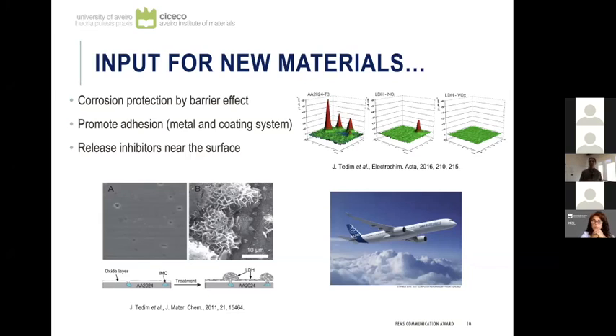organic coatings, but we found out that there was also a need to develop surface treatments with the same properties. And we focused some of our recent research, and we were able to develop conversion films with controlled releasability based on the nanocontainer approach. And we can see here that the development of the conversion film with corrosion inhibitor leads to a significant decrease in corrosion. And this is a pretreatment that has also been co-developed in projects with Airbus.